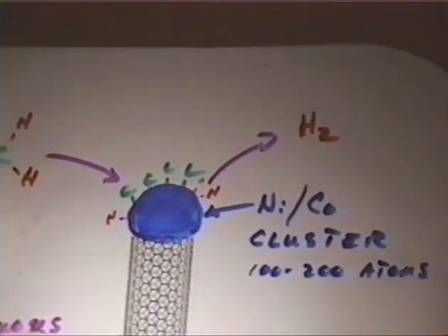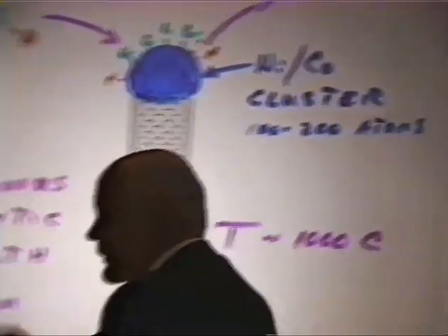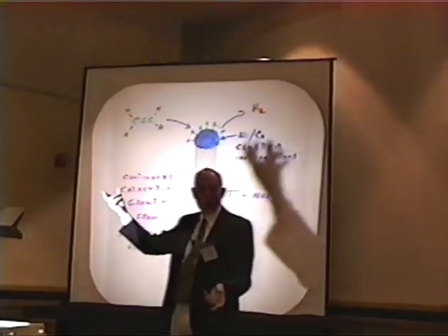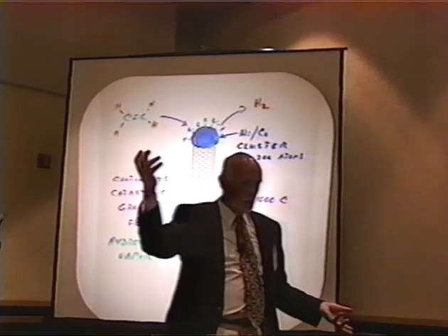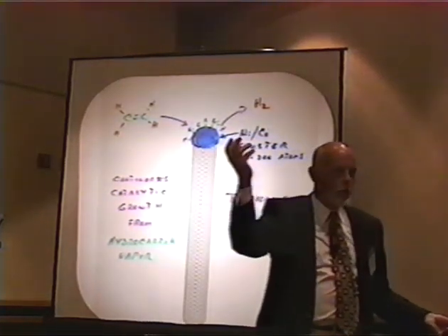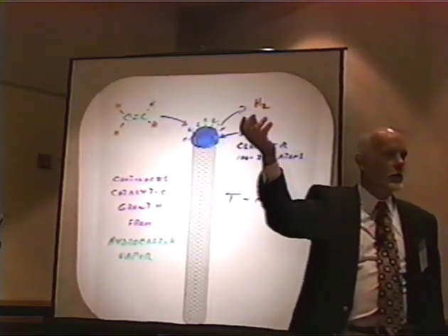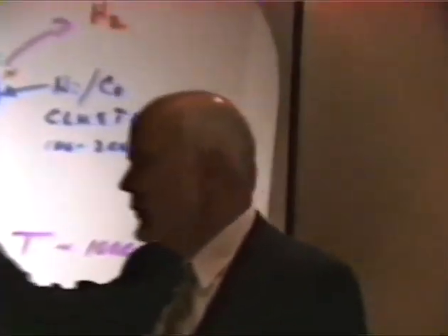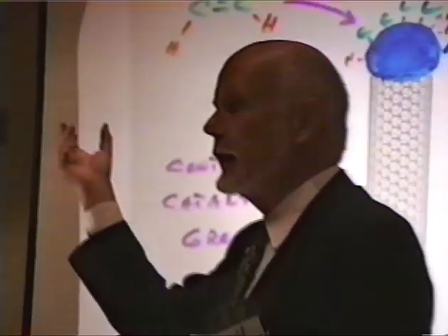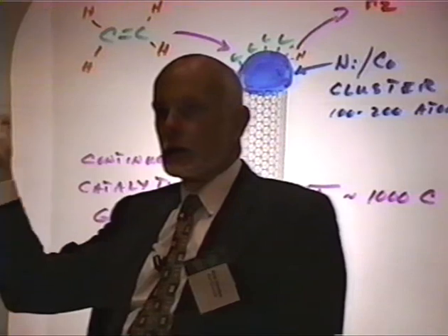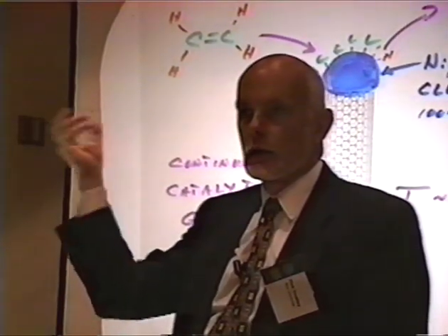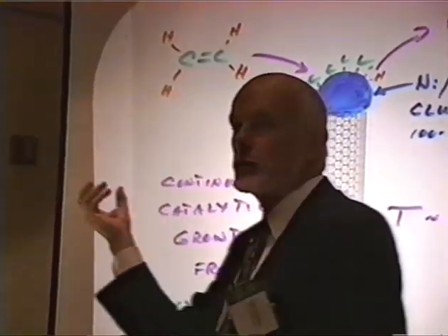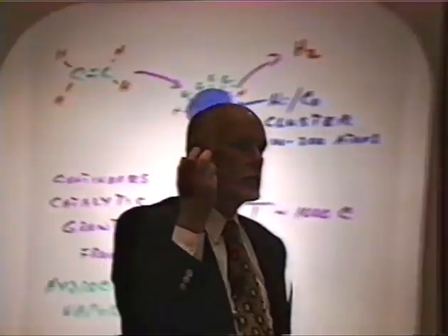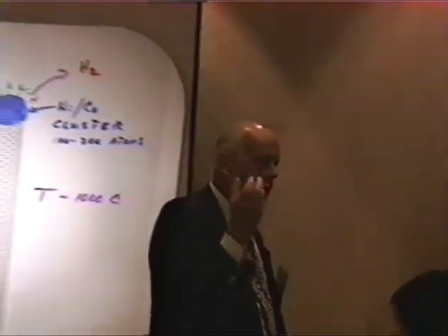I said there was one little seed atom initially back in nucleation, but after it's nucleated and starts to grow, other atoms aggregate, and we know that after a while a little cluster sits there. Well, we know the property of that cluster. It doesn't have to be nickel or cobalt. There's a wide range of transition metals that are active. If you take such a metal cluster at a temperature anywhere near 1,000 degrees centigrade, then you expose any hydrocarbon to it, they'll just rip it apart.